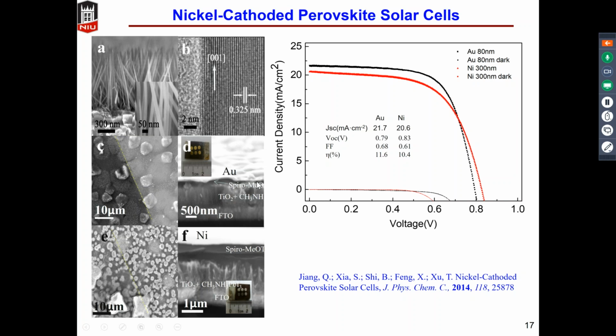But this is not the most important part. The important part is that when we compare the same type of cells we made, when we use gold and use 300 nanometer nickel, we find they are fairly competitive. That means that if we properly coat nickel onto the perovskite and hole transport layer, we should get competitive results, the same or at least competitive efficiency as the gold-based perovskite solar cells.